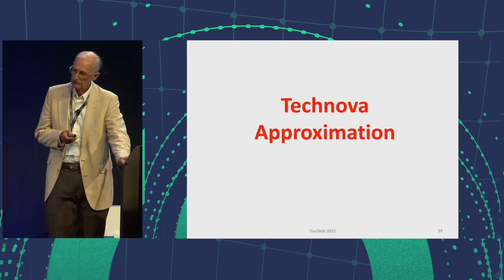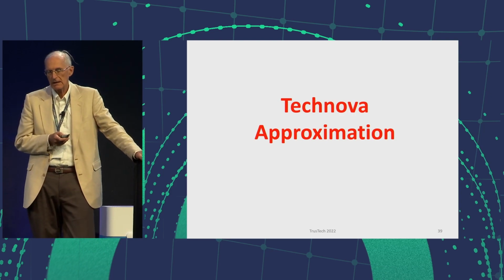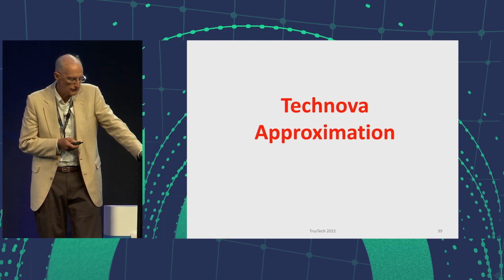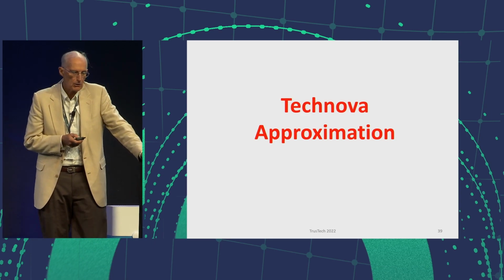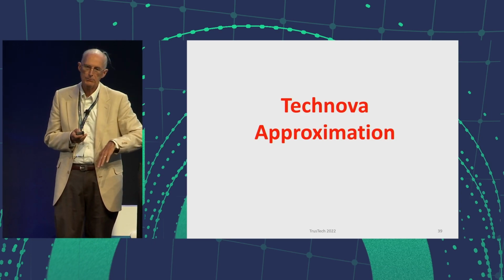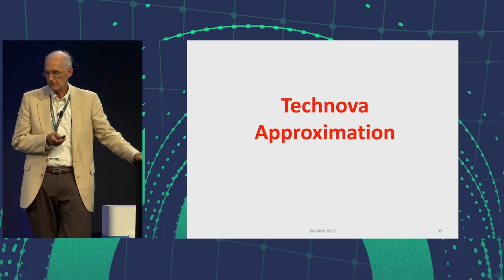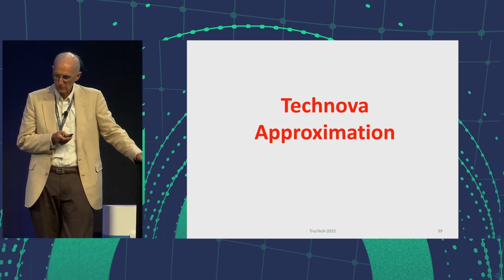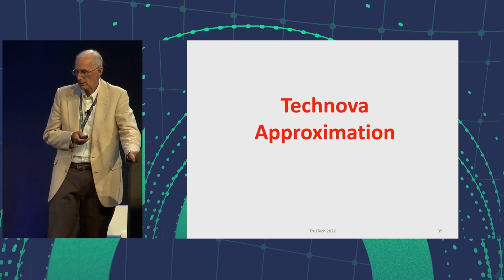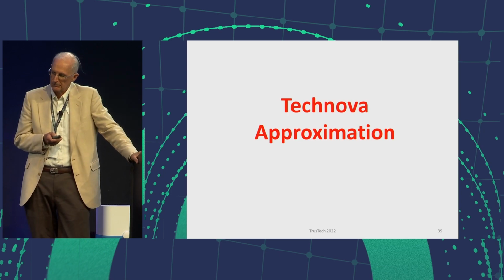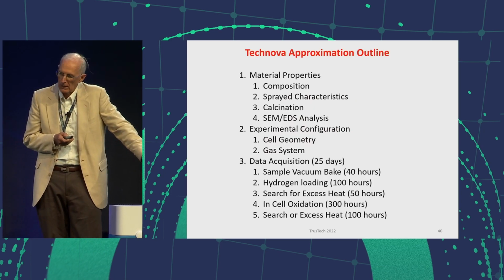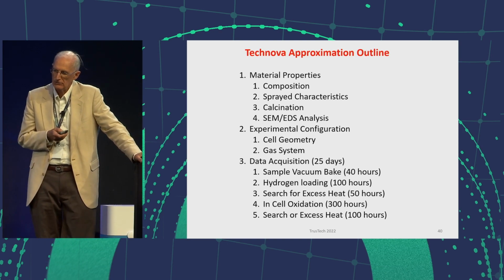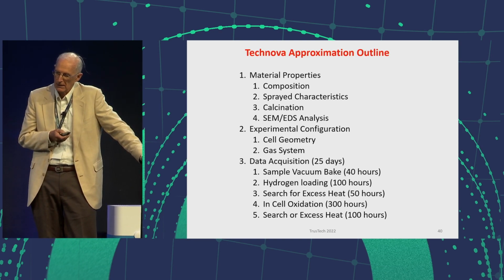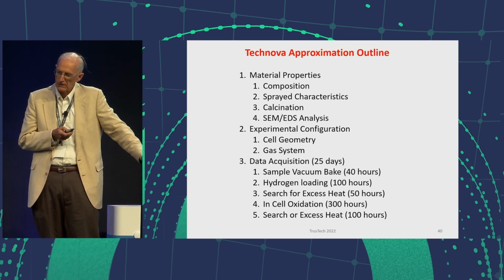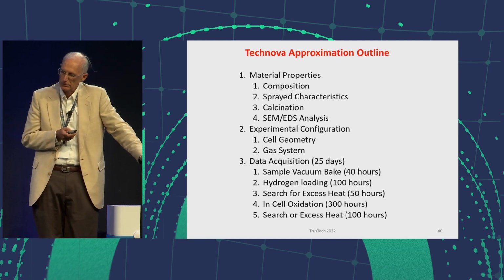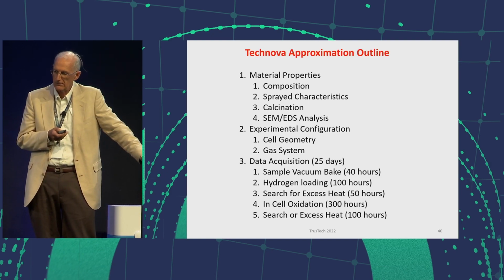The final data is going to look at a Technova formulation of copper, nickel, and zirconium. I call this an approximation because I did not follow their procedures for preparing it, as I didn't have the facility to prepare a spun ribbon as required. It was during COVID and things were closed down. So what I'm going to do is talk about the materials that I used, show you the experimental configuration, and then look at the 25 days of data that I took.